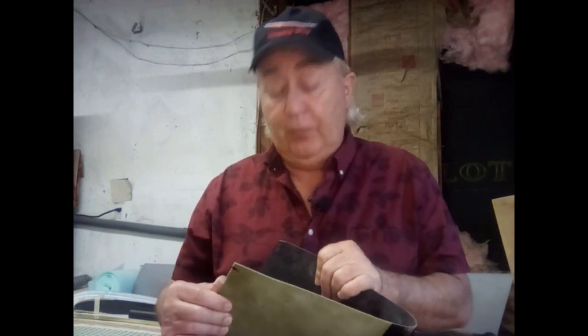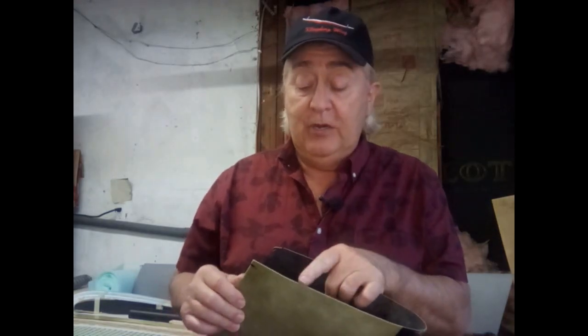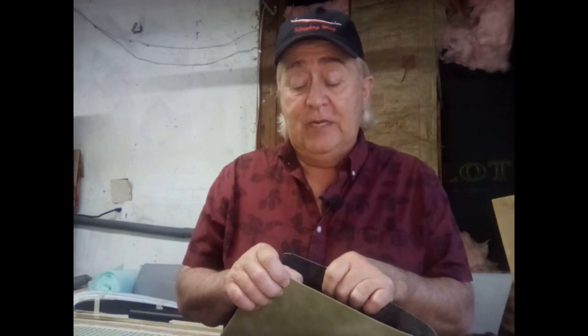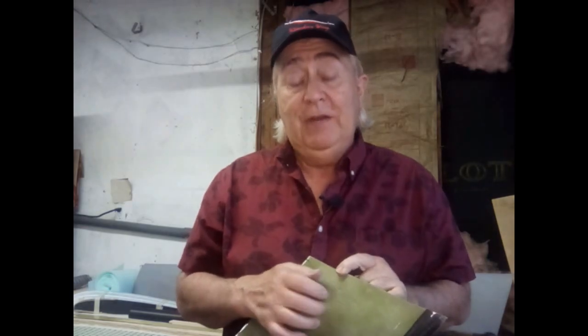And if you've been following with me, you know that this is a sandwich panel construction. It has carbon fiber on the inside, very thin spread tow carbon fiber, I think about 3 ounces per square yard. And then it has a layer of Airex foam at about 3 pounds per cubic foot, and it's 1/16 of an inch thick. And then on the outside, I got one layer of 3-ounce fiberglass, 120 weave. Very fine weave, a smooth finish.